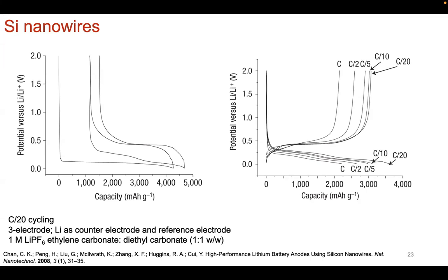What you also see here, cycled at C/20, which is pretty slow, is the achievement of extremely high capacity. Okay, the 4,000 milliamp hour per gram that you expect, and then as you increase the rate capability, the efficiency of diffusion decreases, and you don't achieve as much capacity, but still pretty competitive. 2,000 milliamp hour per gram is nothing to sneeze at, of course. So promising, even though this is a fundamental study, a demonstration of silicon nanowire growth.